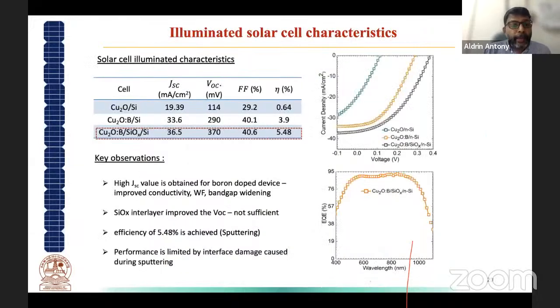And we fabricated a device, a full heterojunction solar cell using a copper oxide and silicon, which showed an efficiency of initially only 0.64%. Then we tried to dope it because it's having a high series resistance. You could see the green one. So we doped it with the boron, which improved the efficiency. You could see this curve to the yellow one.